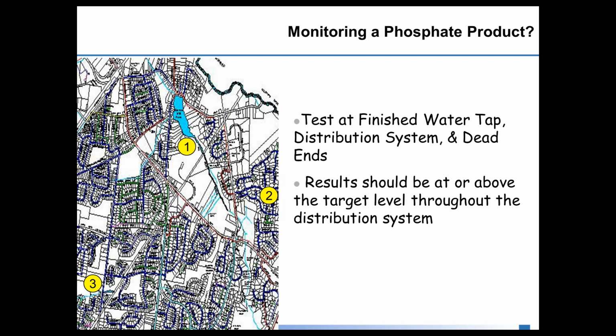Once you've started feeding a phosphate product and have formed a film in the distribution system, that orthophosphate level throughout those distribution points at 1, 2, and 3 on the picture should all be relatively similar. So if your target's 1 milligram per liter after 90 days or 6 months of feeding, you should see about 1 milligram per liter at all 3 points in the distribution system, letting you know that you're forming a coating and have maintained control out in the distribution system.